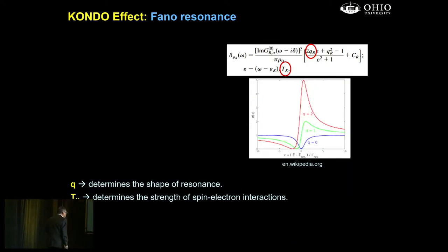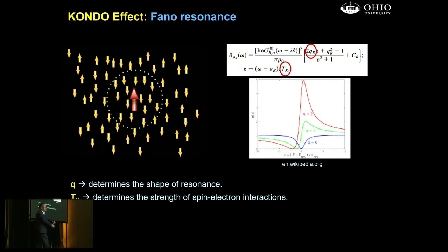What is the peak? Bear with me a little bit. The peak is actually a spin signature. We call it the Kondo effect. What happens is we have free electrons on the gold 111 substrate. When we add one electron, there is a net spin from the electron. That spin interacts with the free electron spins of the substrate. That effect, the Kondo effect, tells us that there is a net spin there.